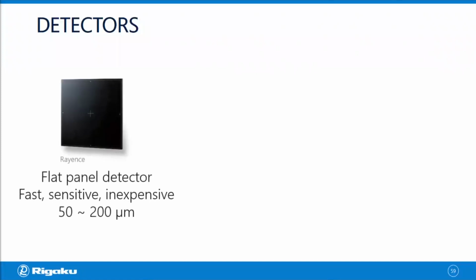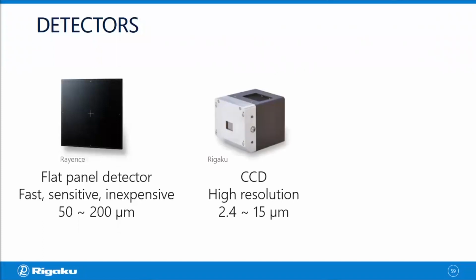Now let's take a look at the detectors. The most commonly used detectors for X-ray CT scanners are usually flat panel or solid state detectors. They're popular because they're fast, sensitive, and inexpensive. Their typical pixel size varies from 50 to 200 microns. And those are great detectors, but if you want to do higher resolution imaging, you need a little bit smaller pixel size. Then you probably want to use CCD in that case. CCDs are available with smaller pixel sizes, and they work better for high-resolution imaging.